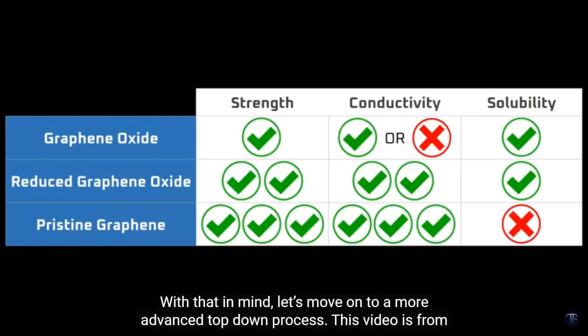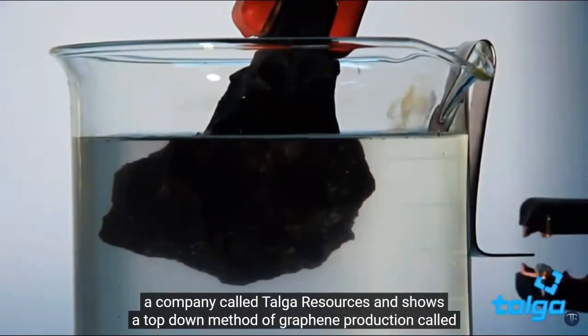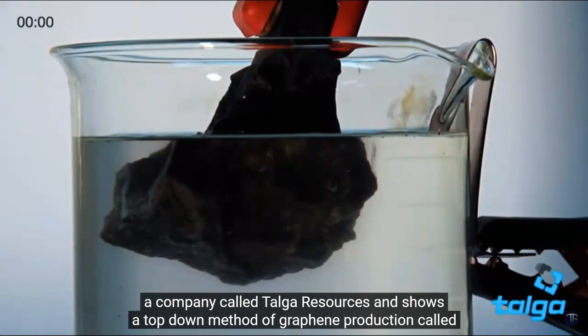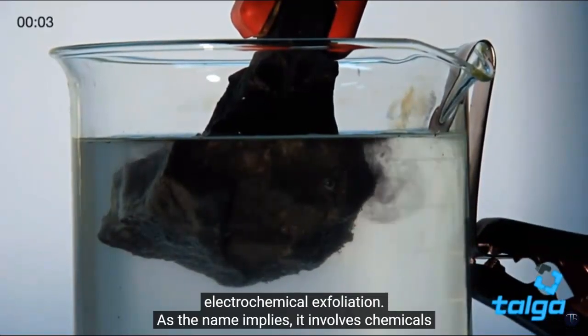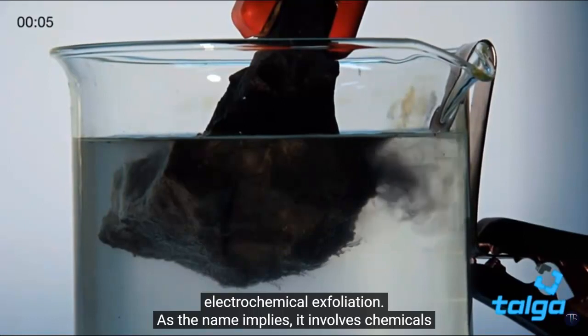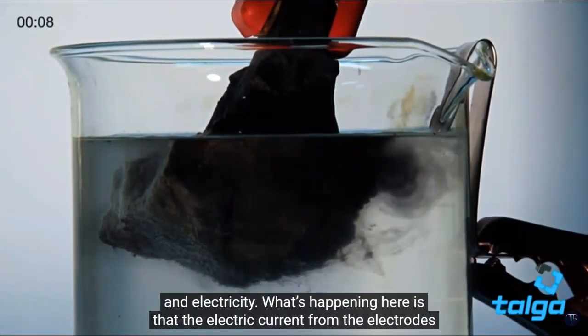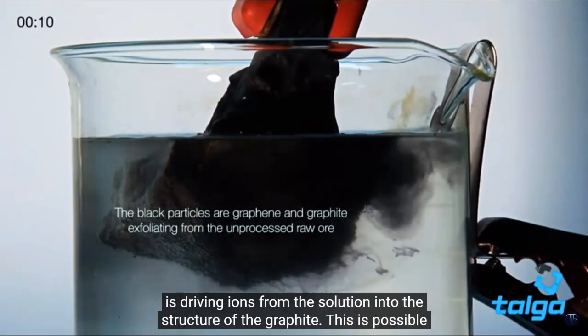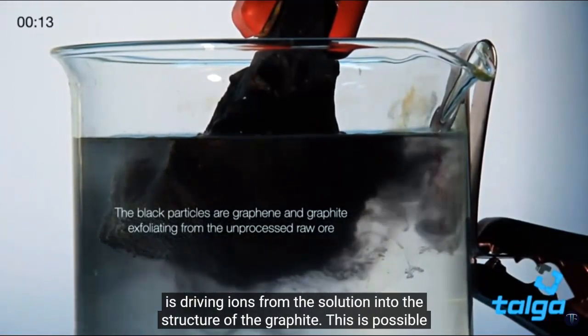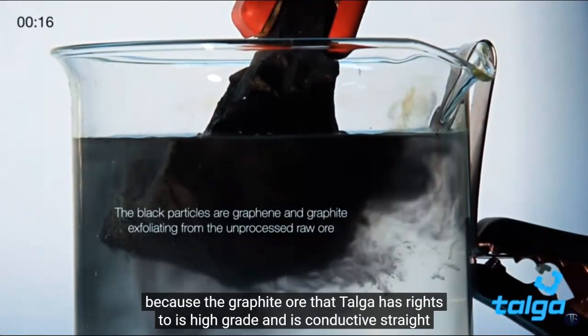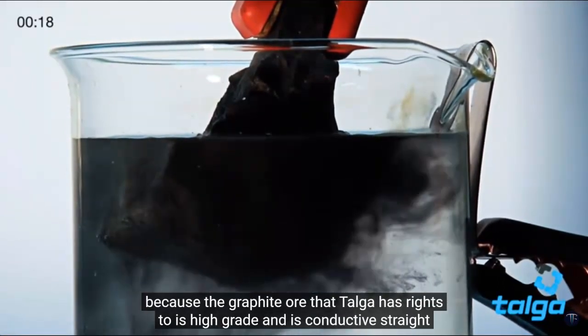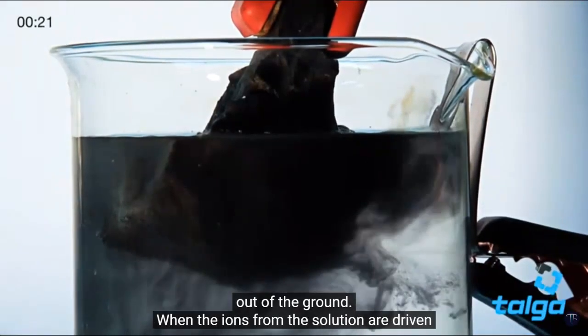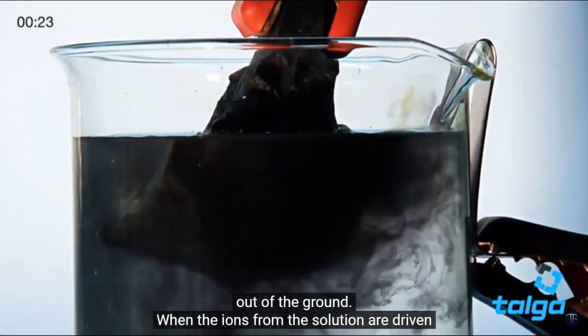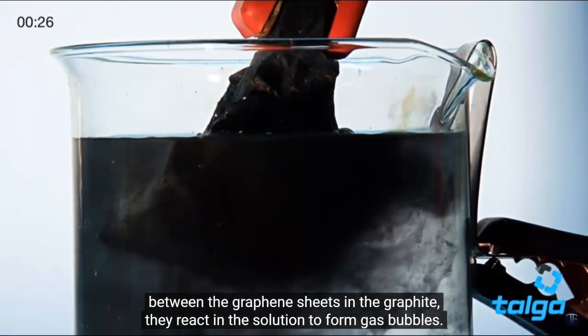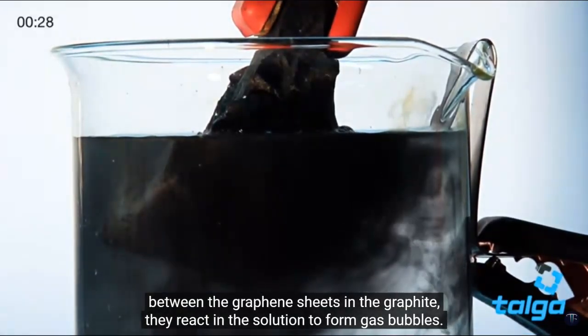This video is from a company called Talga Resources and shows a top-down method of graphene production called electrochemical exfoliation. As the name implies, it involves chemicals and electricity. What's happening here is that the electric current from the electrodes is driving ions from the solution into the structure of the graphite. This is possible because the graphite ore that Talga has access to is conductive straight out of the ground. When the ions from the solution are driven between the graphene sheets in the graphite, they react in the solution to form gas bubbles. The gas bubbles split the graphite layer by layer, causing the graphene to exfoliate.